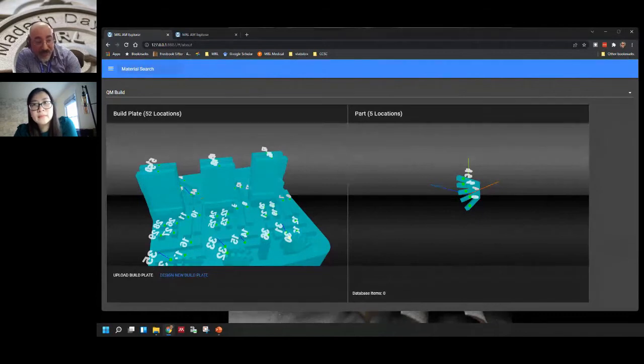As for predicting texture evolution on the subsurface material, that by itself is highly material dependent, and if we are using a net shape material, which is not in this case, but if we're using a net shape material, especially in the topology optimized part, we have another database that we upload to give you an indication what will be the ODF related to it. And the texture here is the crystallographic texture. We are not talking about surface roughness, what sometimes is referred to as surface texture.